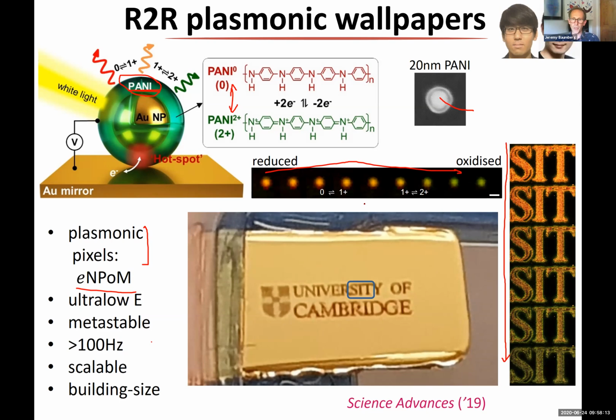The voltage that you need to change them is on the order of something like 0.4 volts. So there's a very, very low voltage, but the system is bistable or metastable because you're essentially doing redox on this polymer. And as long as you exclude oxygen from the system, it will stay in the same state. But because the distance that you need to pull electrons in and out from the system is so small, you can actually drive the system very fast. We have some evidence that you can actually drive it even at megahertz frequencies, but certainly greater than 100 hertz.